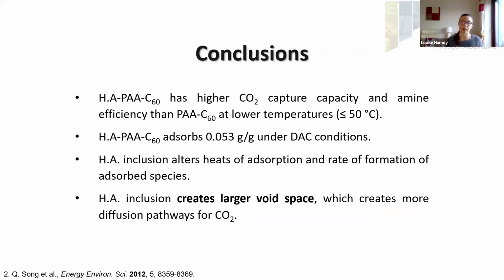So to conclude, we have developed a new adsorbent, which has a higher CO2 capture capacity and higher amine efficiency than its analog material, which doesn't have a hydrophobic additive. And it's a better adsorbent at lower temperatures. Under direct air capture conditions of 400 ppm and 30 degrees, it adsorbs 0.053 grams per gram. This is competitive with other polyamine-based adsorbents. The inclusion of the hydrophobic additive alters the heat of adsorption, as we've seen, and also the rate of formation of the adsorbed species. So the hydrophobic additive increases the void volume. It gives us larger void spaces, and this opens up better diffusion pathways for the CO2.